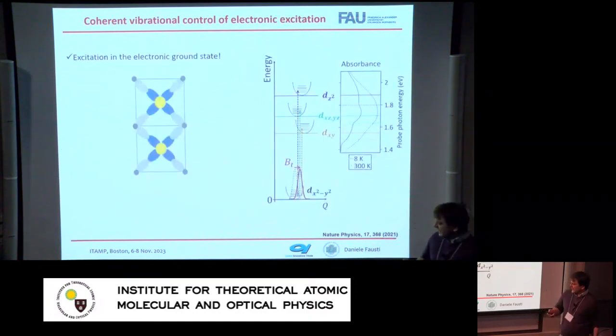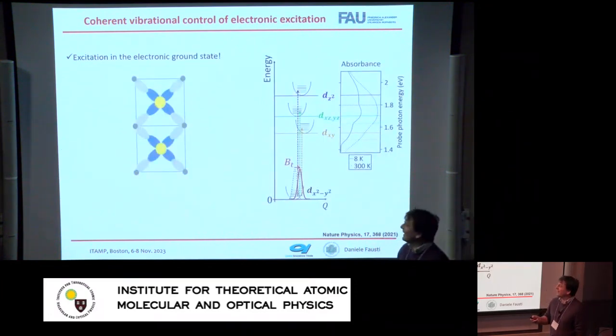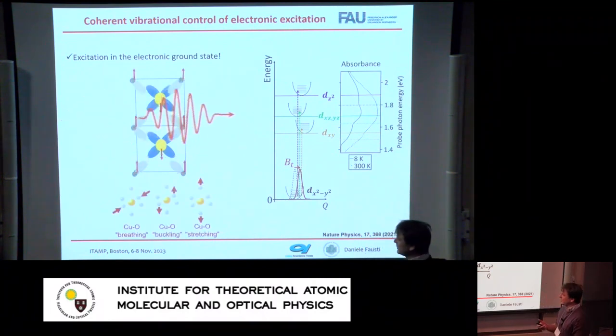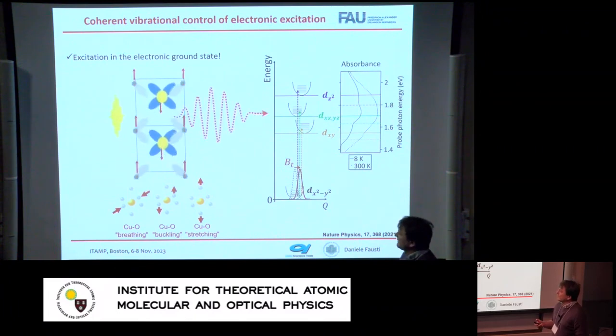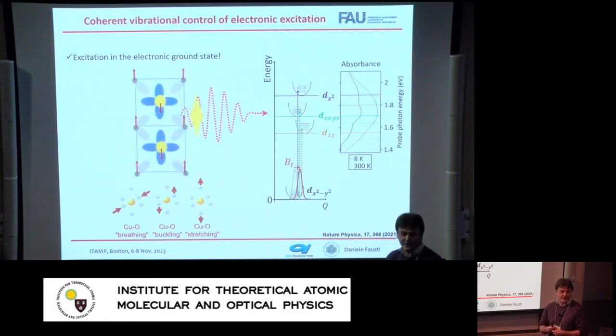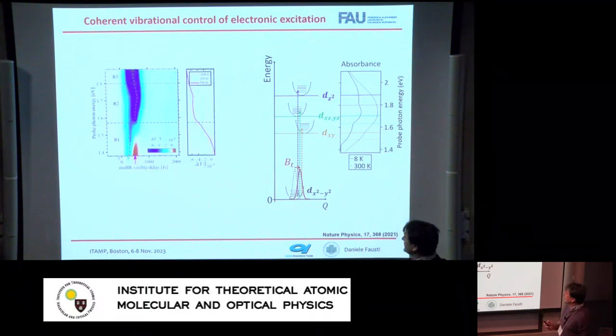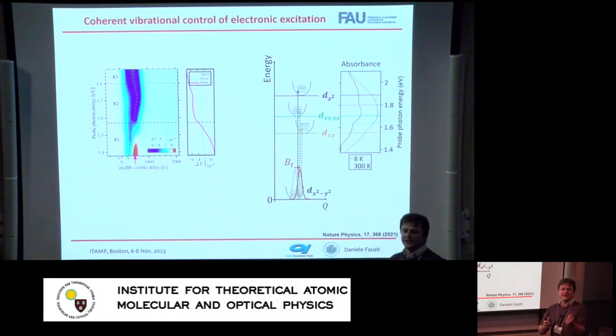So this was for us the ideal platform, because whenever I can drive a vibrational mode, very similar to what, as I said, Andrea showed before, I can try to ask myself, how does this driven vibrational mode modify the electronic absorptions? And the results, which I summarized just in one slide, it's essentially one of the situations which is interesting, because if you look at the optical absorption at equilibrium, when I increase the temperature, I always increase the absorption, in the sense that if I think that this absorption is mediated by thermal disorder, the more I increase the vibrational disorder, the more I will absorb. And that's visible in linear absorption.